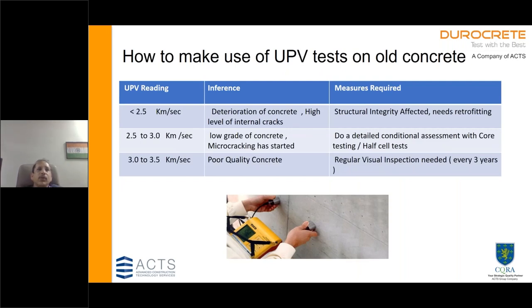Another test that we do is UPV of old concrete. Generally, for UPV tests, there's a code, IS 516, that divides concrete into different types of integrity. But a UPV reading of less than 2.5 certainly indicates that there is internal deterioration of concrete and a high level of cracks. A UPV reading of 2.5 to 3 km/s will certainly indicate that micro cracking has already started inside.